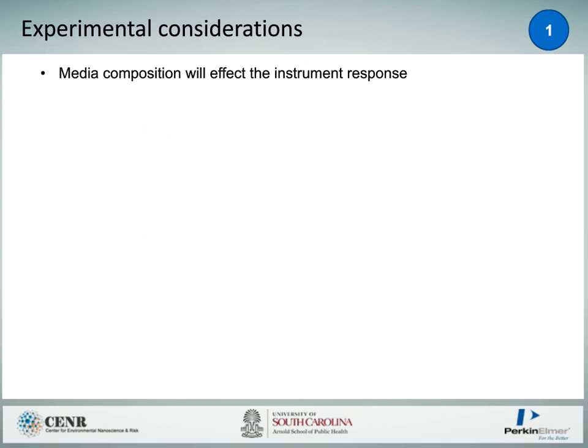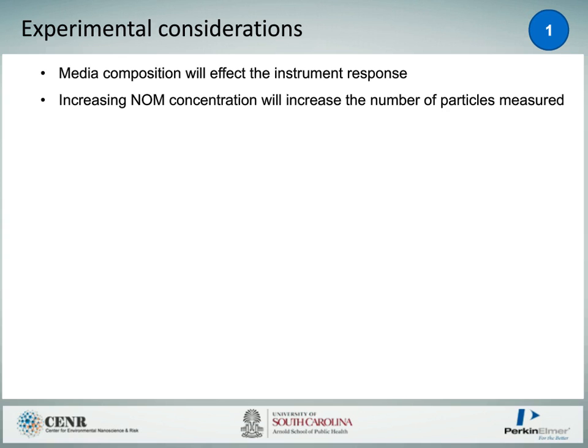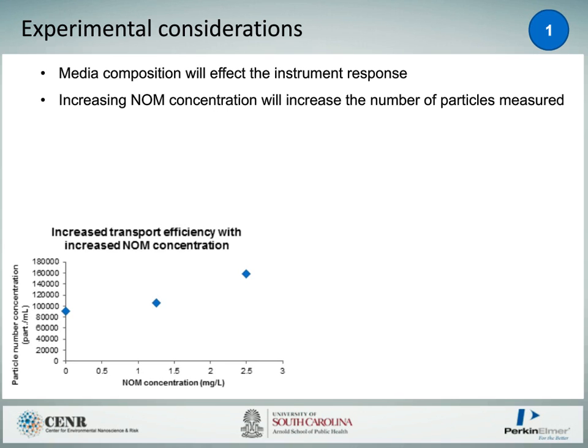So experimental considerations for this. If we have a media composition, this will affect the instrument response. So increasing natural organic matter concentration will actually increase the number of particles measured. So we did a study where we did the ionic calibration and the nanoparticle transport efficiency in ultra-high pure water, and then added natural organic matter to the known amount of nanoparticle. And you can see as you add natural organic matter to your system, we end up actually getting more nanoparticles per mil. We haven't actually got more nanoparticles per mil, but we're changing the way that the instrument responds.